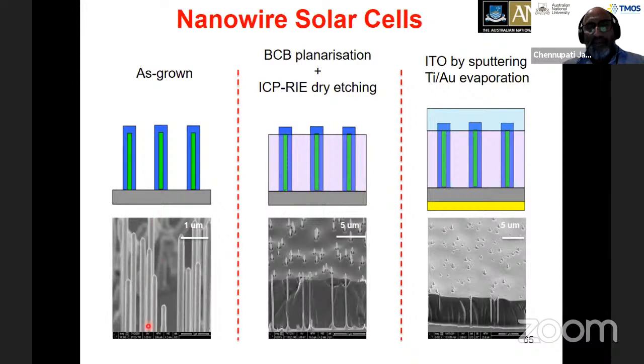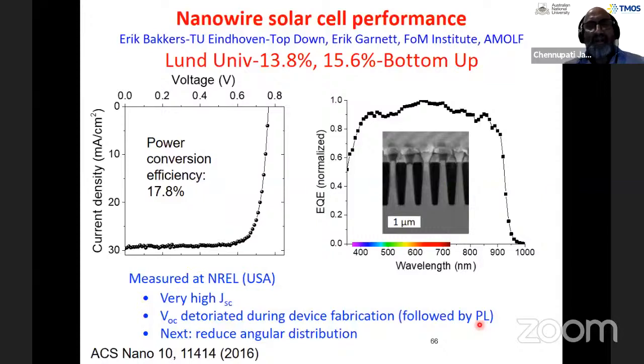So here's a case where, again, we have grown these structures of this schematic here, the gallium arsenide, aluminum gallium arsenide nanowires. Then we fill this with the polymer material and selectively etch, as I mentioned earlier, like we've done for LEDs, and put some indium tin oxide and put some contacts at the top and the bottom, and then shine light and look at the current generated from these solar cells. Again, to cut the long story short, my colleagues at Technical University of Eindhoven, Professor Erik Bakkers and also Professor Erik Garnett, FOM Institute in Amolf, have demonstrated 17.8% efficient solar cells. These are some of the most efficient solar cells reported in the literature to date, which looks very promising for future applications, for example.